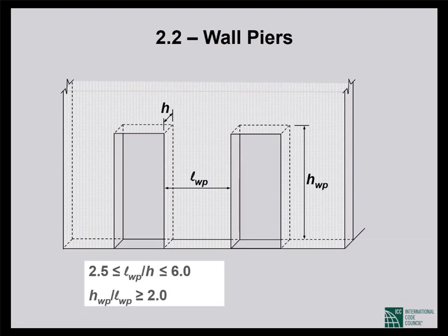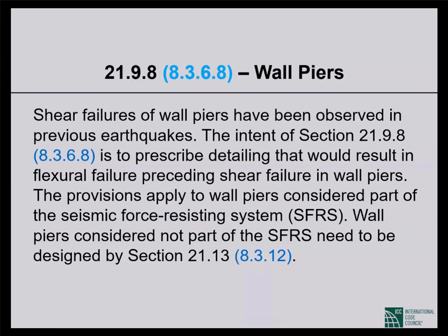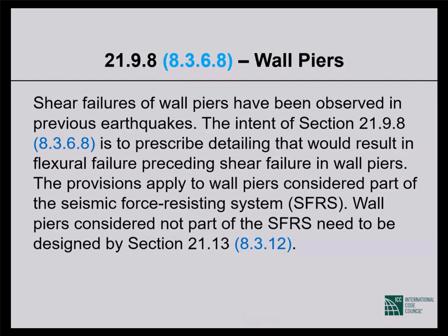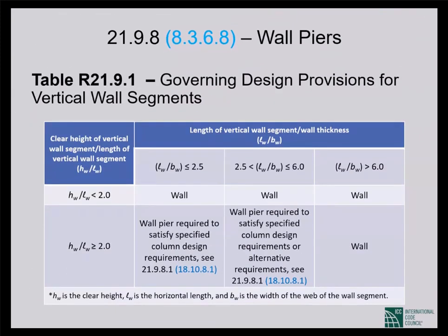In that range, the element is particularly vulnerable to shear failure. So shear failures of wall piers have been observed in previous earthquakes. The intent, anyway, let me go to the bottom line, what it is that we have done in 318. This is a table from the commentary, which I think explains the whole thing extremely well. So if the height to length ratio is less than 2, this is clear height of vertical wall segment divided by length of vertical wall segment. We were not calling them piers because they may or may not be piers. As long as it is less than 2, we have walls, irrespective of the length to thickness ratio.